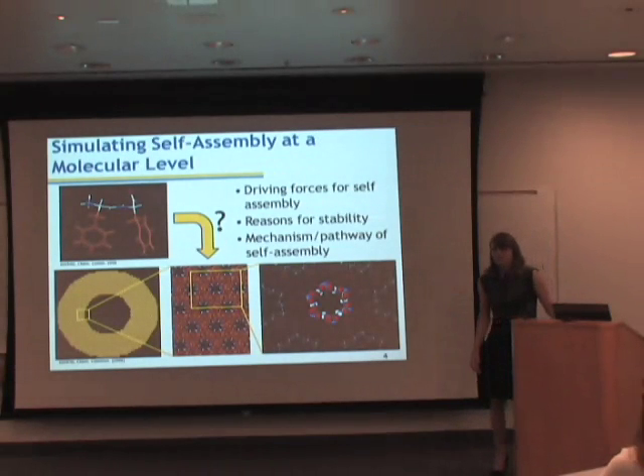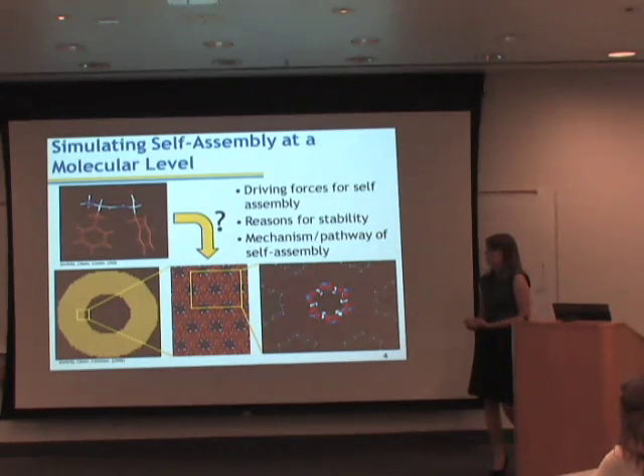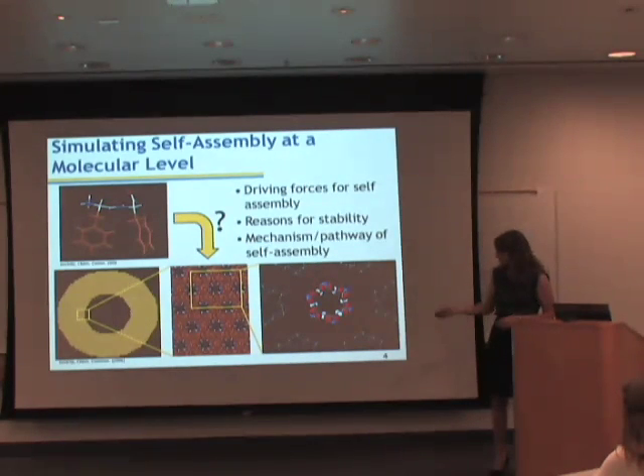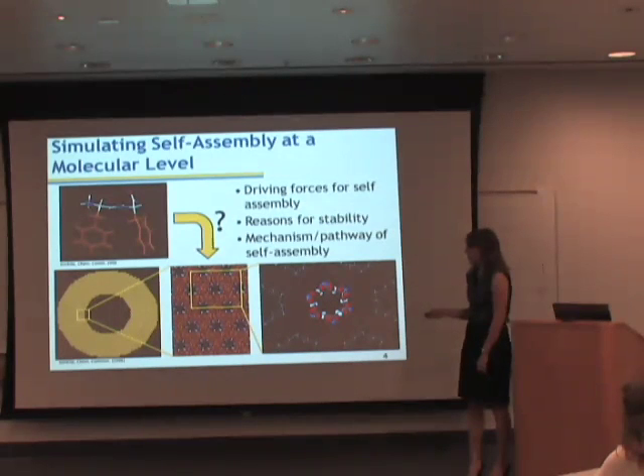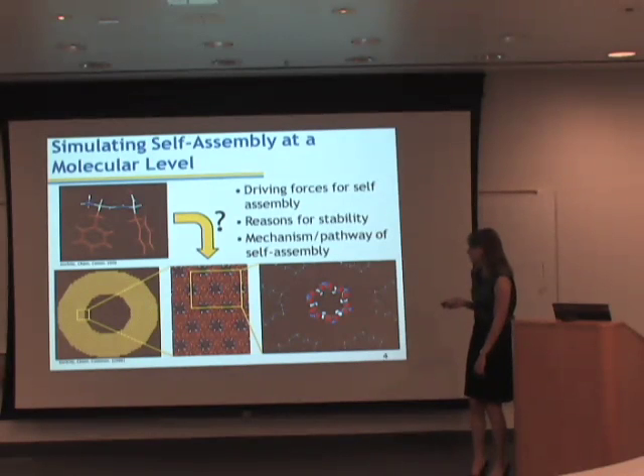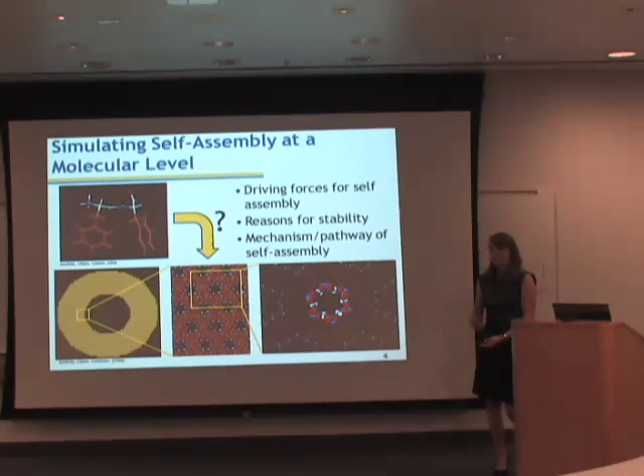In addition to having many unique applications, diphenylalanine nanotubes also have an extremely unique crystal structure that is shown here on the bottom. So I'll walk you through what this crystal structure is. This yellow tube here is a cross-section of a diphenylalanine nanotube. If we zoom in on these little black dots that are dispersed throughout, we find that they're actually pores, which fill with water when the nanotubes form.